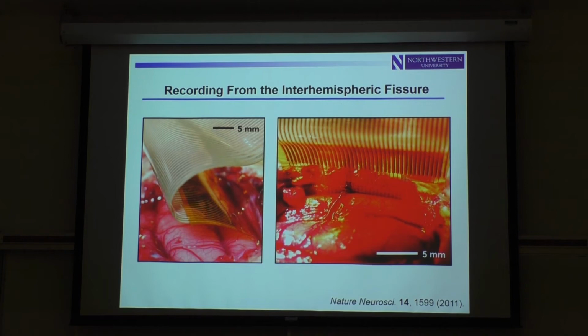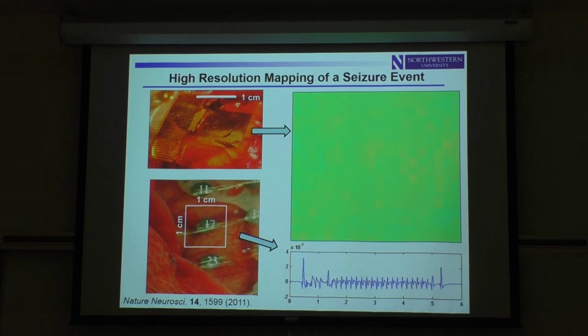So here's some data that shows you what kind of measurements you can make in this type of platform in the relative length scale. This is a color rendering of patterns of electrical activity associated with a seizure. This is output from a single representative channel in this overall array. And here we've artificially induced a seizure by use of a pharmacological agent, picrotoxin. So we induce the seizure here. We see a lot of anomalous electrical activity in this spatiotemporal map. You see it here in this single channel extracted from that map.